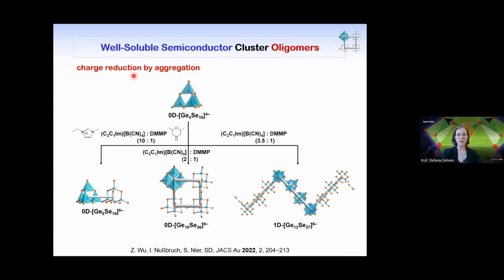There is a second way of reducing the charge and making clusters soluble, and this is by aggregation. And here it's important to play with the precursor ratios. So what we have is the imidazolium cation from this ionic liquid, and then we add an auxiliary like this amine here, and we can play with its numbers and then get aggregations into dimers or tetramers or infinite zigzag chains. And of course, this affects two things.